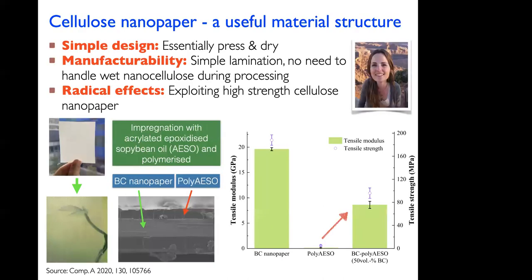We decided that instead of trying to replace water — a difficult process — we would have our nanocellulose hornify significantly, creating cellulose nanopaper, and use that paper as our reinforcement. The paper properties come from the properties of the nanofibers themselves. In one study, wet nanocellulose — bacterial cellulose — had water removed by simple filtration, then pressed at elevated temperature to dry. Essentially paper making. A nice piece of cellulose nanopaper was then impregnated with a soybean oil resin by simple lamination, and once polymerized, produced a composite that is surprisingly transparent.